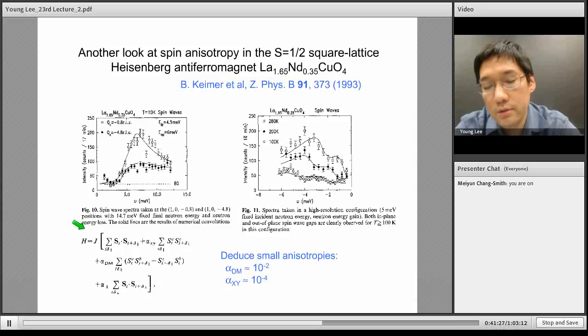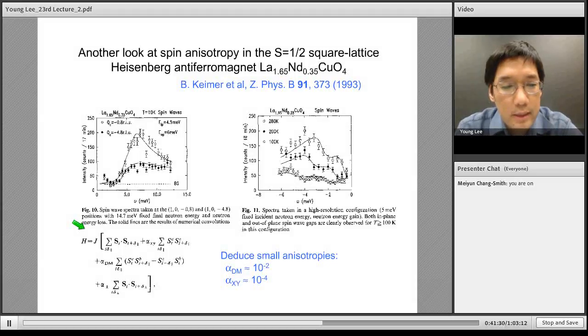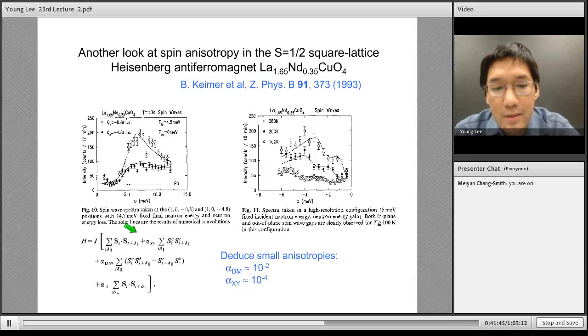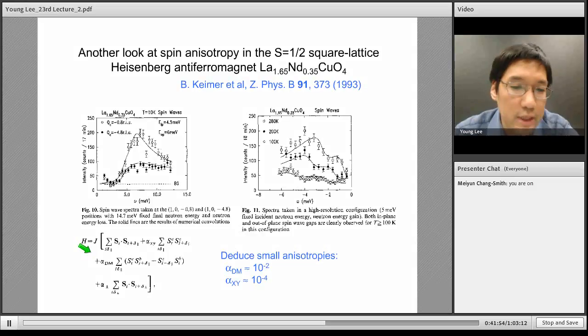So in addition to just the basic Heisenberg exchange J, we can figure out what are these small perturbations with some very good precision. So there's this alpha xy, which is telling us about the anisotropic exchange, and the Dzyaloshinskii-Moriya interaction over here, which is the anti-symmetric exchange. And the basic idea is the same. So this is work by Keimer and co-workers.